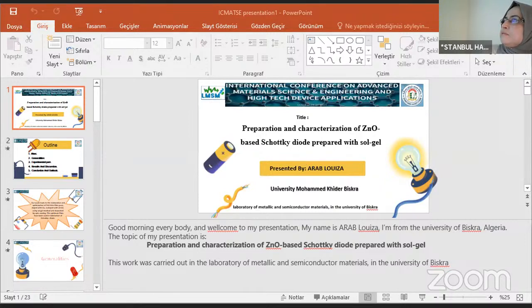For the glass substrate, we notice that for zinc oxide doped with gallium and co-doped, we have recorded a lower value of disorder energy, which improves the quality of this film, and a high value of gap energy.